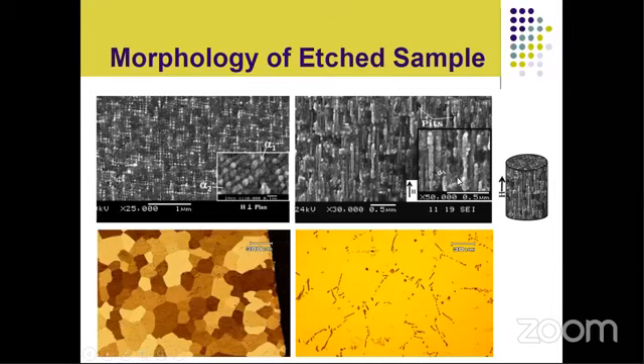Here you can see the rod length. It varies, from almost 0.5 micron to something like 0.1 or 0.2. But when we look at this material from the top, it looks like dots. These are shown in the higher magnification view. Here you can see the micron marker is 0.1 micron. So one dot is almost less than 100, I think 50 to 60 nanometer.